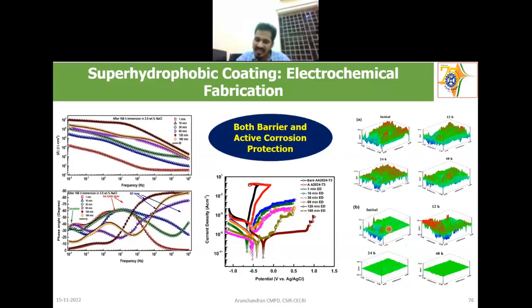But in the case of the cerium-doped one, I mean the cerium stearate electrodeposited coating, I could see some anodic peak initially. The corrosion is happening initially, and at 12 hours it increased. At 24 hours, I could see that it completely stopped here. Electrochemically neutral areas emerged up to 48 hours. So a kind of self-healing or active corrosion protection is offered by the cerium stearate also, in addition to the super hydrophobicity. The improved corrosion protection was also observed from the dynamic polarization studies and electrochemical impedance studies.